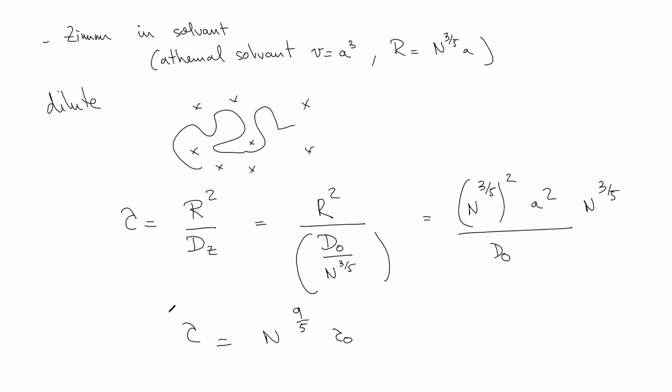So the time scale for relaxation in a realistic Zimm picture is a monomeric time scale for relaxation as before, but the exponent is not 3/2, it is in fact 9/5 if you are really exact on the spatial properties of the polymer chain. Okay, so that's just a correction from what I said previously, because now we are entering into first order description.